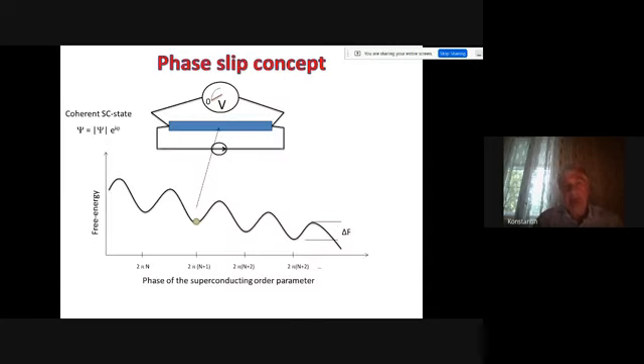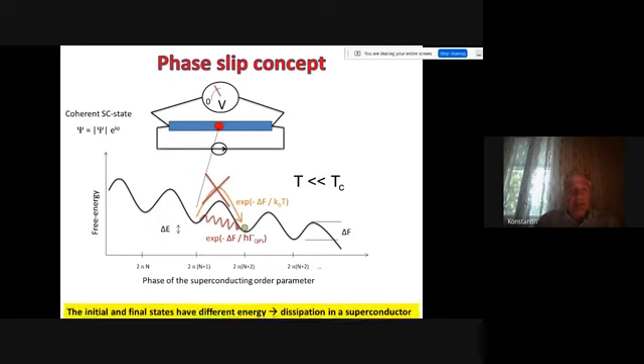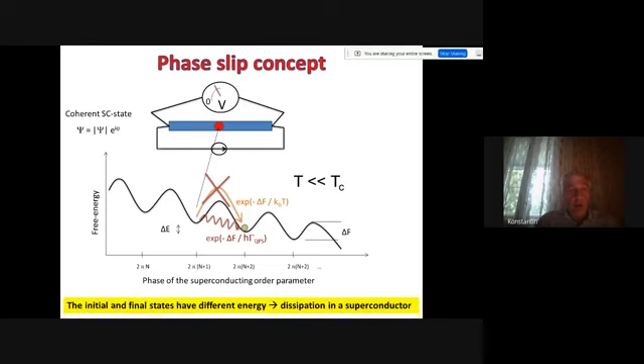Here is another, let's say, hand-waving explanation of what happens. If we select some particular point in a nanowire and plot the dependence of free energy on the phase of the superconducting order parameter, then there are two options for the system to go from one local minimum to another. First is to go above the barrier, and this is the effect of thermal fluctuations, which is most pronounced in superconductors at high temperatures close to the critical temperature. But as it is a quantum system, there is a possibility that the system tunnels from one local minimum to another. And this is the limit of quantum fluctuations, which is mostly the subject of my talk.